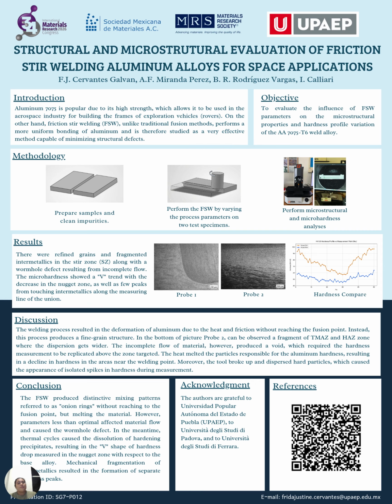For the conclusion, we have that the friction stir welding produced distinctive mixing patterns referred to as onion rings, without reaching to the fusion point but melting the material. However, parameters less than optimal affected material flow and caused the wormhole defect. In the meantime, thermal cycles cause the dissolution of hardening precipitates, resulting in the V shape of hardness drop measured in the nugget zone with respect to the base alloy. Mechanical fragmentation of intermetallic resulted in the formation of separate hardness peaks.